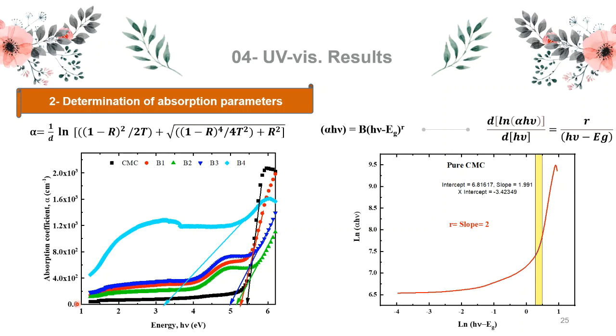The absorption coefficient of the produced samples was determined using the obtained transmittance and reflectance values utilizing this equation. Plotting the coefficient of absorption against the energy of the incident photons reveals the position of the absorption edge, as can be seen by the arrows in the figure. Extrapolation of the linear part of the curve for all samples to the energy axis gives the value of the fundamental edge. A continuous redshift may be seen in the graph with increasing copper oxide concentration, and this indicates the decrease in the optical band gap. Additionally, the appearance of 2 absorption shoulders in all the nanocomposite samples confirms the presence of 2 values of the optical band gap.